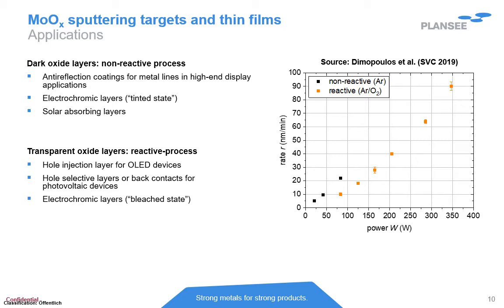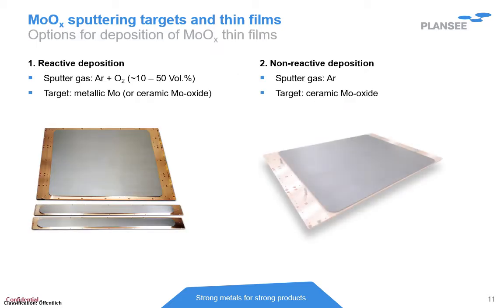On the right chart here, you see an overview of the deposition rate for non-reactive and reactive sputtering processes using a ceramic oxide sputtering target. These results have already been published a couple of years ago, also on SVC. For depositing thin films of molybdenum oxides, there are two possibilities. The one is reactive deposition, using a metallic molybdenum target or a ceramic molybdenum oxide target and adding oxygen content in the sputtering gas, which is quite interesting if you would change the stoichiometry of those thin films in a broader range, but maybe it's more difficult on large area as you really have to achieve a very good control of the oxygen distribution in the sputtering chamber.